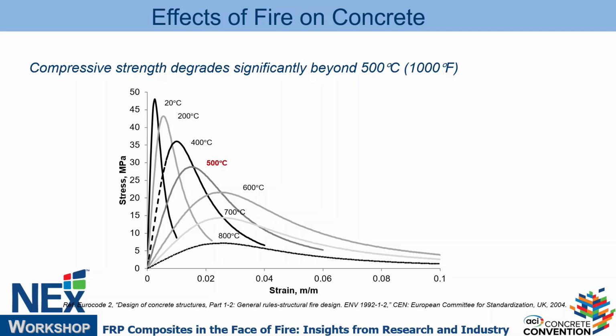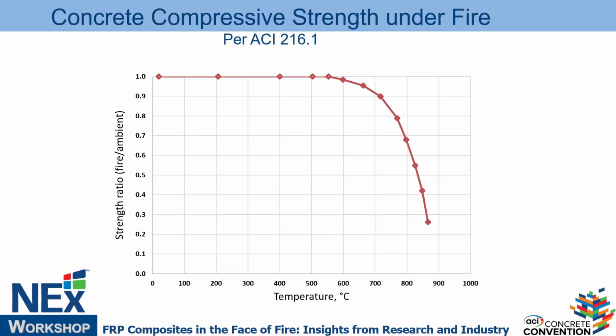So that keeps happening with the concrete, and there are different curves used to represent those. This is the curve that I'm going to show next that comes from ACI 216, and this is going to change a little bit, because even based on my experience I've seen some evidence that the concrete starts degrading at a lower temperature than what shows in here, which is close to 500 C. At 200, 300 C, you can see signs of loss of strength, and I think the new curve in 216 will show a little bit more aggressive loss of strength in concrete.